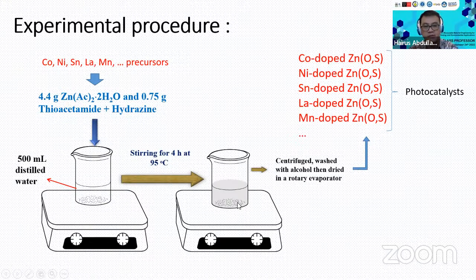So actually, zinc will react with the sulfur from the TAA to form a zinc sulfide phase. However, because of the addition of the reducing agent, some of the zinc is reduced and then becomes reactive with oxygen. That's why there are two kinds of anions in the one zinc sulfide-based phase, right?